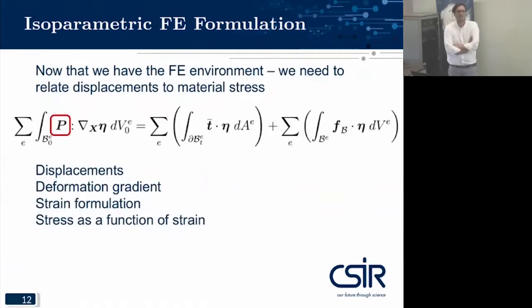As I said before, what I looked at is the stress formulations and how to implement different material models into existing finite element packages. Again, you have displacements, and from your displacements over an element using its isoparametric shape functions, you can derive deformation gradients and use that to determine the material deformation in terms of strains. You can calculate the stresses out of that and pull that back up into the higher system equation.